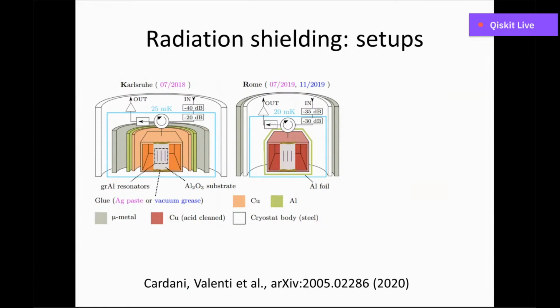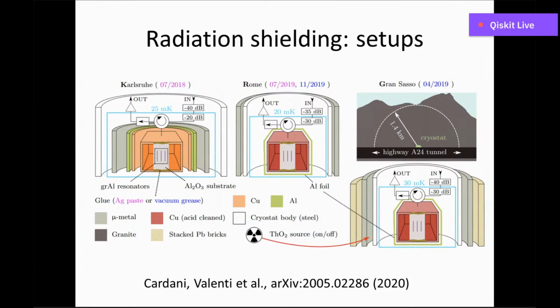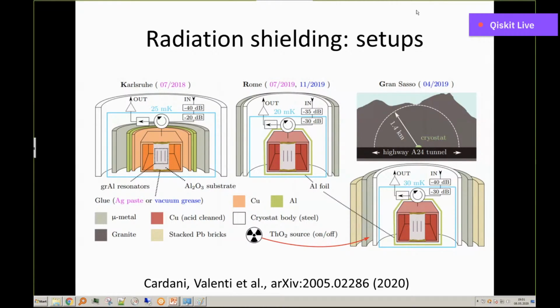Then we have a setup where we cleaned to get rid of local radiation. And as we can see, our copper, that I show now with a different color, was cleaned with acid etching. We performed 2 runs in this setup, one with silver paste and one with vacuum grease. And finally, this is our setup with both strategies applied, cleaned and shielded. The clean waveguide was brought in the cryostat under the Gran Sasso mountain, and the cryostat there was surrounded again by a mu metal magnetic shield and by a wall of lead bricks.